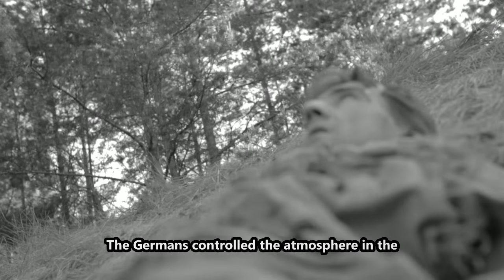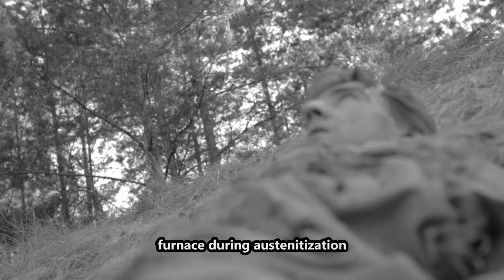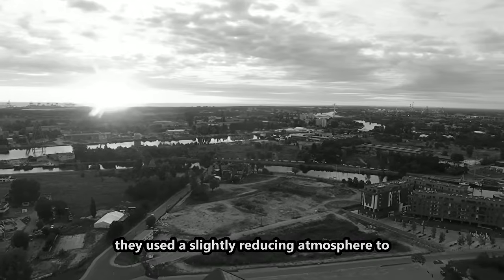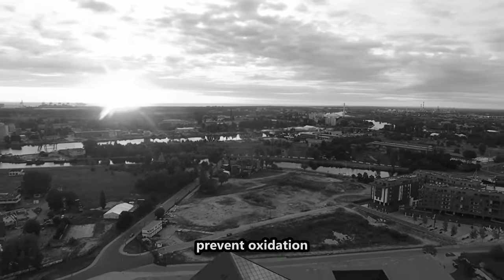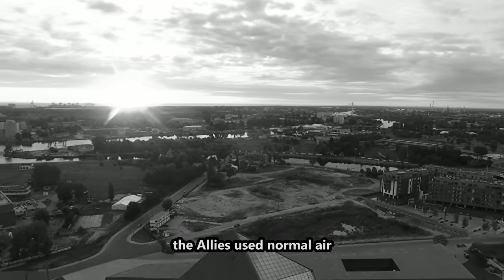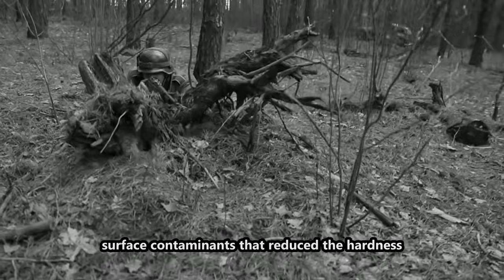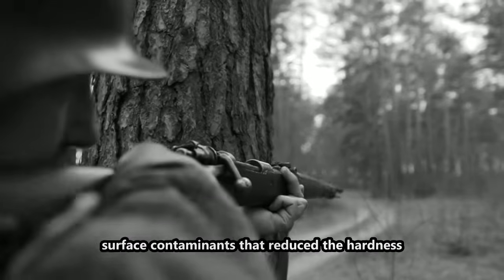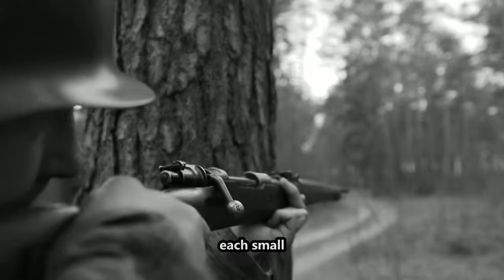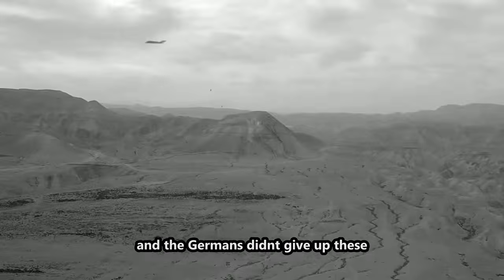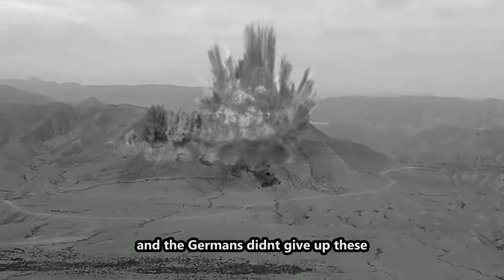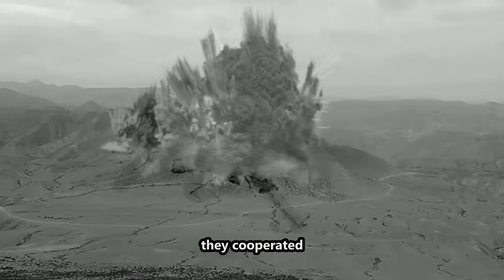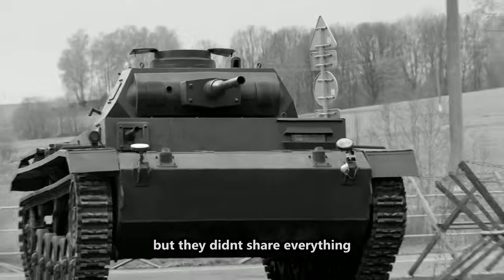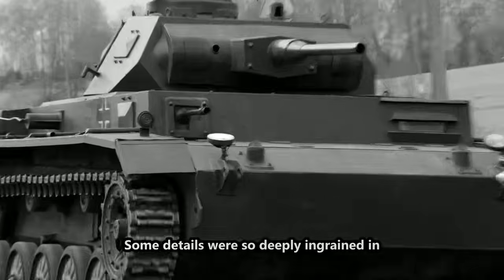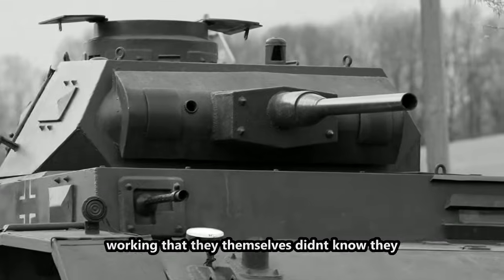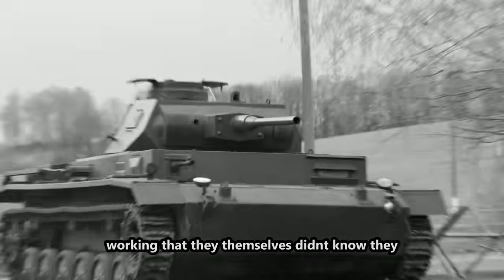A third example. The Germans controlled the atmosphere in the furnace during austenitization. They used a slightly reducing atmosphere to prevent oxidation. The Allies used normal air. Result? Surface contaminants that reduced the hardness. Hundreds of such details, each small, together crucial. And the Germans didn't give up these details, even under captivity. They cooperated, yes, but they didn't share everything. Some details were so deeply ingrained in their way of working that they themselves didn't know they were important.